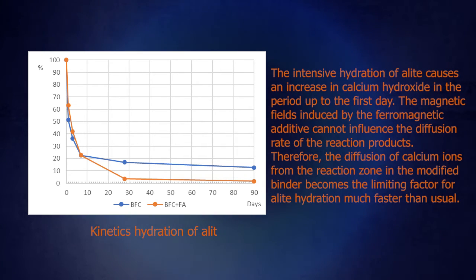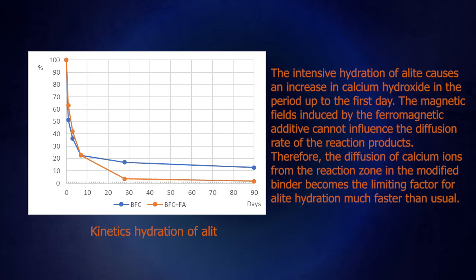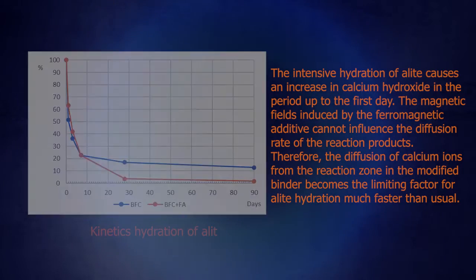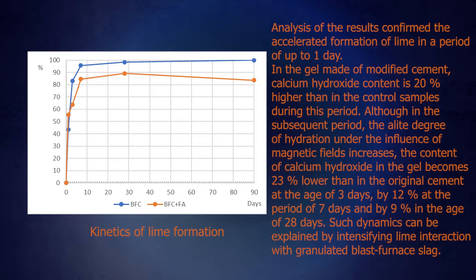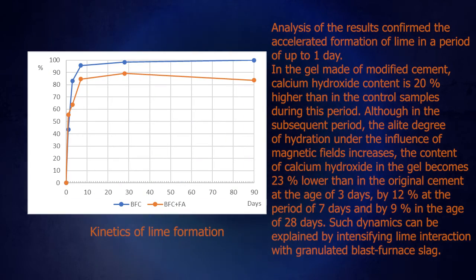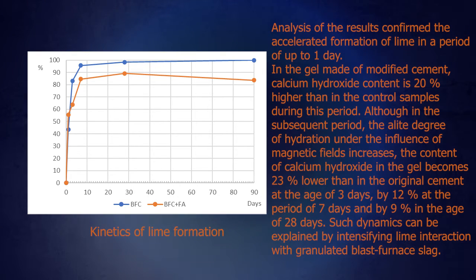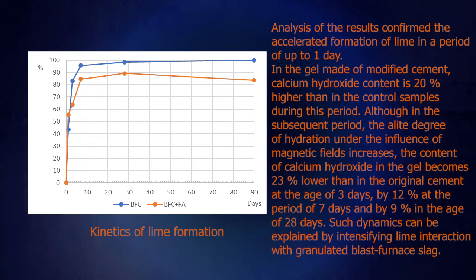Therefore, the diffusion of calcium ions from the reaction zone in the modified binder becomes the limiting factor for alite hydration much faster than usual. Analysis of the result confirmed the accelerated formation of lime in a period of up to 1 day. In the gel made of modified cement, calcium hydroxide content is 20% higher than in control samples during the period.